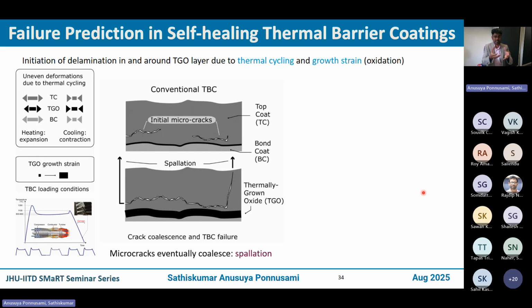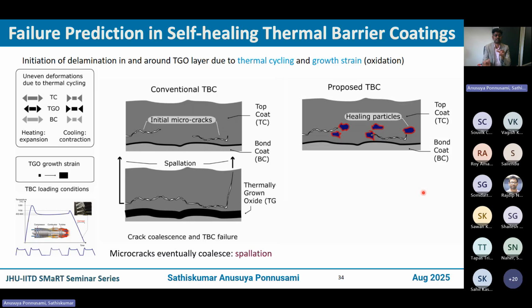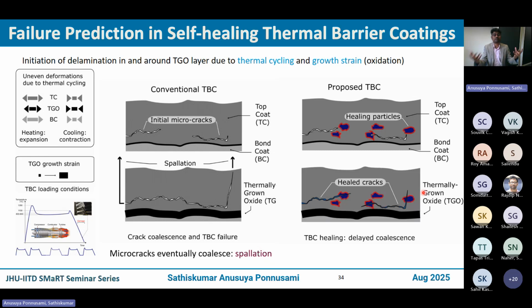So if you don't prevent it, these cracks coalesce, form a major crack, and then the ceramic coating falls off and exposes the underlying metallic components. So that is what we proposed here as part of the EU and Dutch government project: we incorporated healing particles. Without getting into the physics of this particular problem, what happens here is these healing particles enable healing of these cracks.